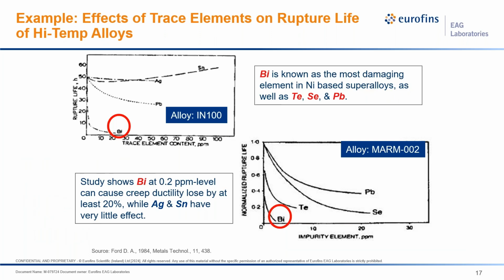Here is an example that some of these foreign elements present in these high temperature alloys have a damaging effect on their mechanical strength at high temperature. For instance, bismuth, even at 0.2 ppm level, which is 0.2 microgram per gram, can cause creep ductility loss by at least 20%, while silver and tin have very little effect.